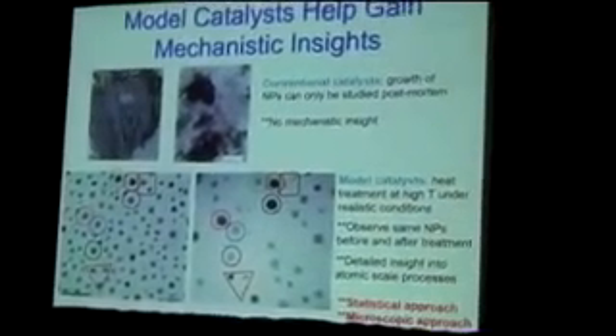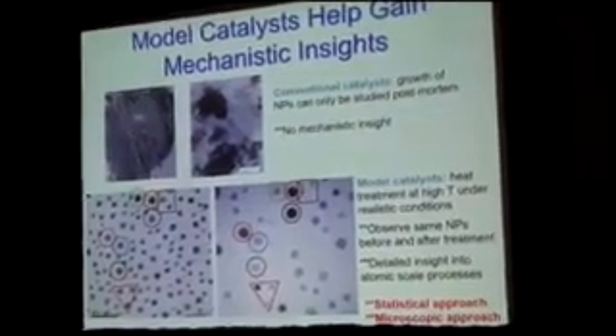These kinds of questions you cannot answer on the real catalyst, because you can only do a cross-section on the automotive catalyst at the initial stage and after aging. Now you can say, yes, there's a lot of synergy going on. But the model catalyst that comes included right over here allows you to see the same region of the catalyst after heating in air to 790 degrees, whatever you want, in your electron microscope, and you can see that this is really all happening. The particles are disappearing, you can overlay the images one on top of each other, and there's hardly any mobility at all. The level of mobility is associated with the support, which is not perfectly stable, so there's a little stretching going on. But other than that, we use the model catalyst approach.